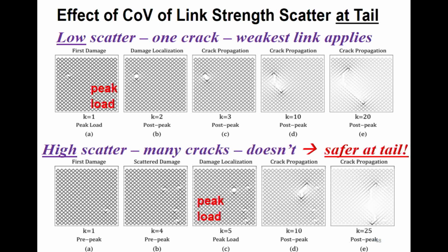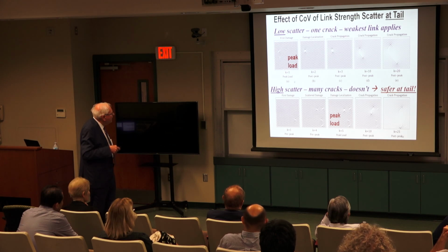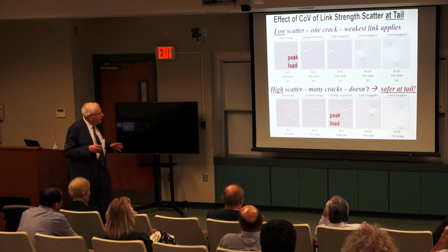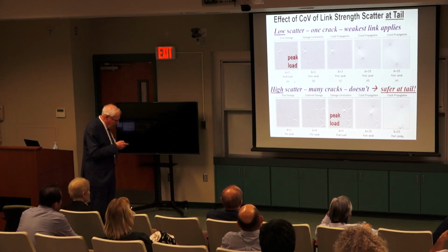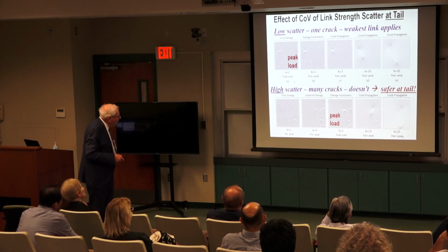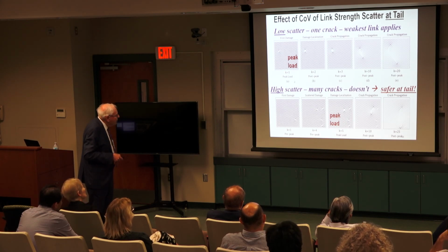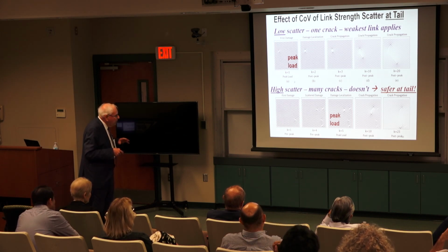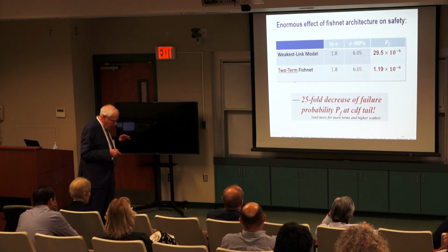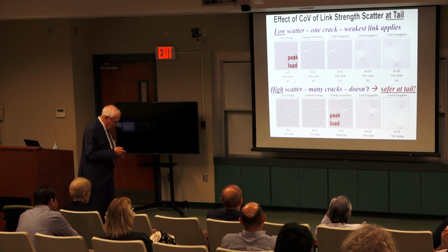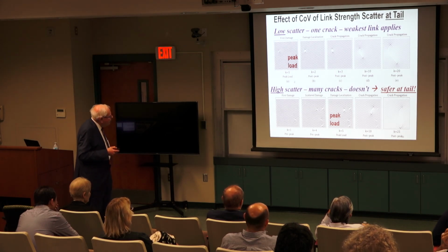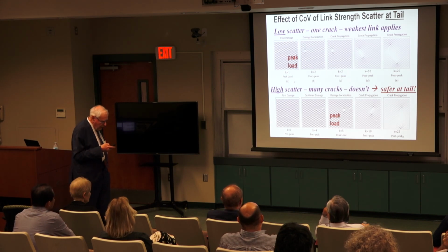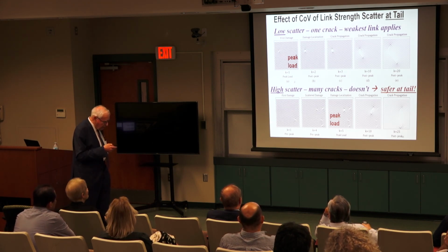Now, interesting is the role of scatter. Actually, very interesting. At low scatter, the peak load occurs very early, typically at the first element. If there is no scatter, perfect geometry, it would fail with one link. That's it. But as the scatter increases, peak load happens after much damage, as you see here. These are actually simulations of this fishnet you see here exactly. So high scatter may weaken the material in the mean, but can make the tail very much safer. Very much safer. So this is a very useful property to know. So sometimes scatter is good actually in these materials. We should not aim at most homogeneous structures.